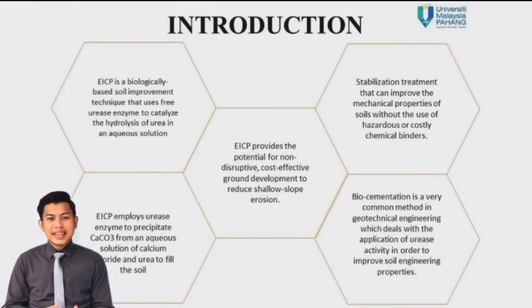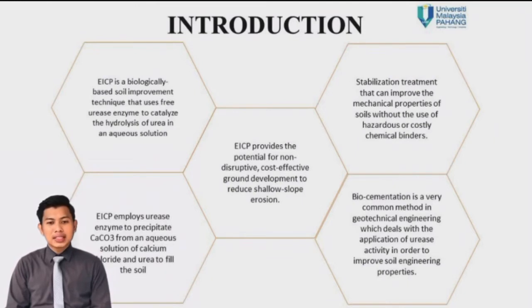What is EICP? EICP is a biology-based soil improvement technique that uses free urease enzyme to catalyze the hydrolysis of urea in an aqueous solution, producing carbonate ion and alkalinity that, in the presence of calcium cation, leads to precipitation of calcium carbonate.